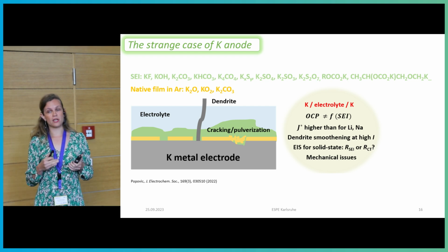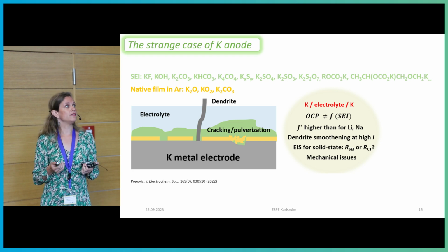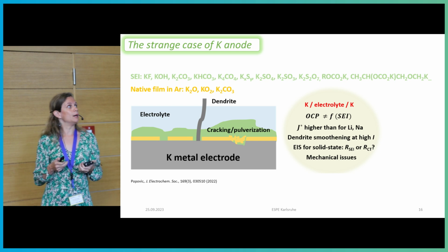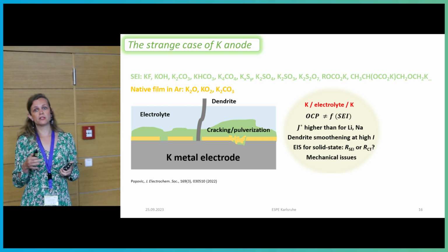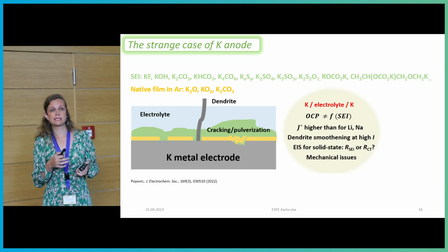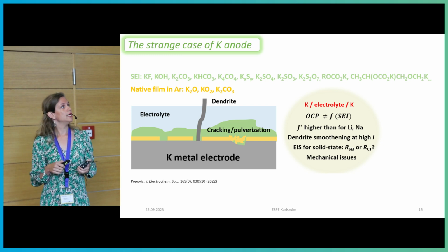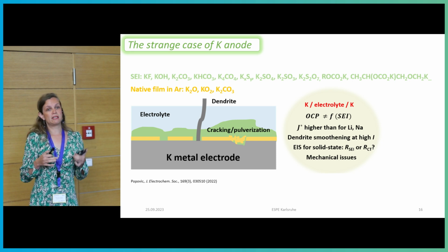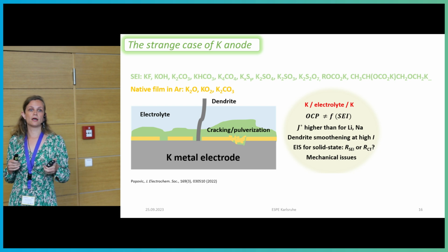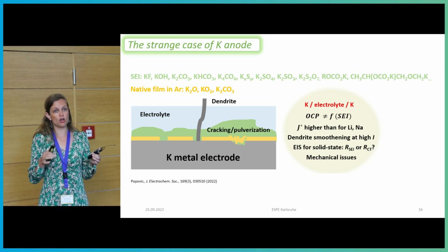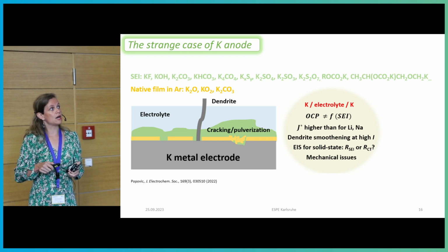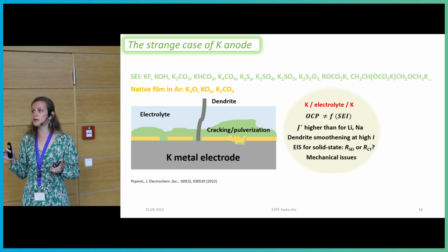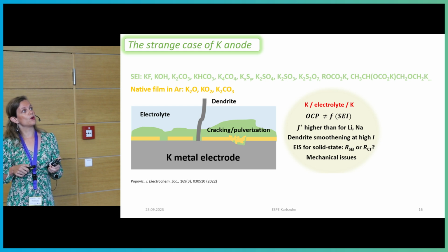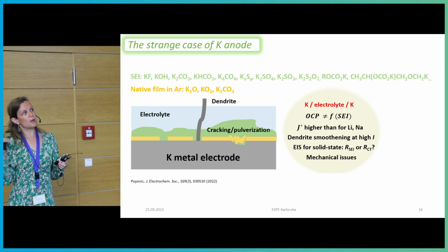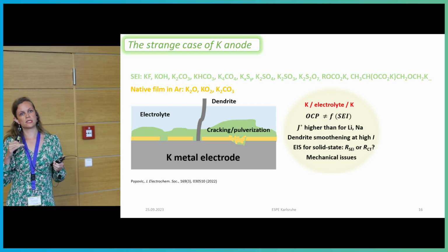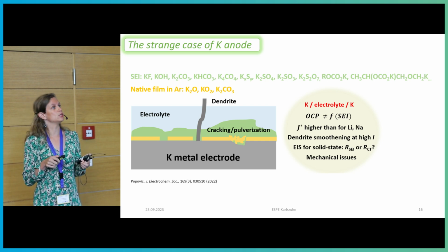And then I wanted just to stress that potassium is a really exciting alkali metal because it's so much more complex than lithium and sodium. It, first of all, has a much larger zoo of materials possible in the SEI, but also the native film is slightly more complex because we have a peroxide also forming. And there have been speculations that the fact that people do not get zero OCV voltage is related to SEI. I dare to say that it is not. It's always the end phases that define the OCV. But what is kind of positive is that the crossover current might be higher than in the case of lithium and sodium because we might have a kind of surface smoothing, since the diffusion coefficient of potassium on the surface of metal is much higher than in the lithium and sodium case.